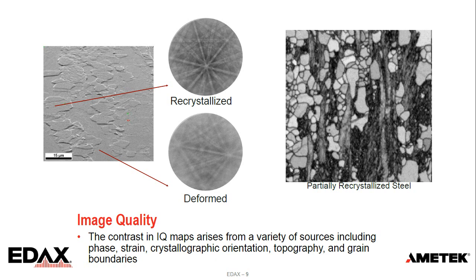Topography and grain boundaries. As we come closer to grain boundaries, the patterns can start to overlap and the overall intensity decreases. So this slide just shows an example of a recrystallized pattern and a deformed pattern. You can see the sharpness difference. You can kind of see the intensity difference, but if we map that out on a grayscale map, you can clearly see the recrystallized grains are bright and equiaxed. The deformed grains are much darker and more elongated in the microstructure.